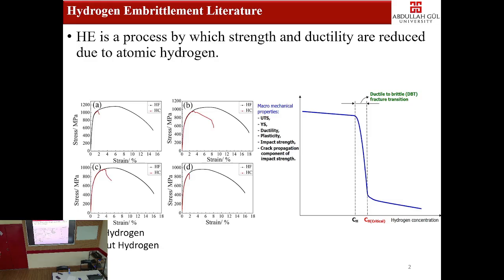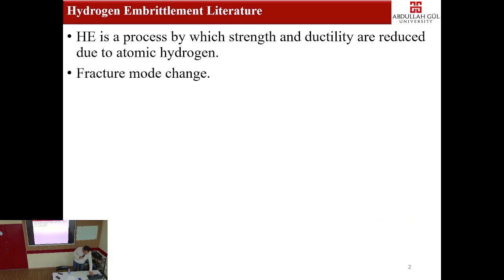So let's start with some basics in hydrogen embrittlement. After some amount of atomic hydrogen, we see a dramatic decrease in macro mechanical properties, like the ultimate tensile strength. Sometimes we see an increase in yield strength, but ductility is reduced, impact strength is reduced, toughness is reduced, even at quasi-static strain rates and also high strain rates. We have some experiments. So hydrogen causes a problem in metals, and we have to understand what this problem is.